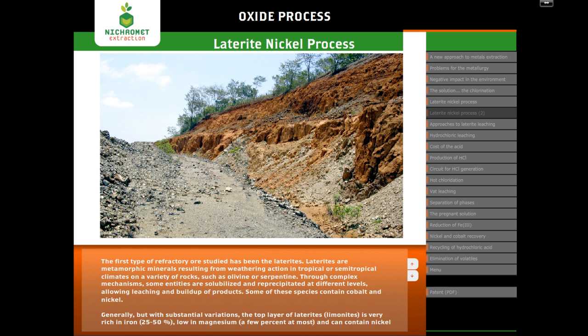Through complex mechanisms, some entities are solubilized and reprecipitated at different levels, allowing leaching and buildup of products. Some of these species contain cobalt and nickel. Generally, but with substantial variations, the top layer of laterites, limonites, is very rich in iron, low in magnesium, a few percent at most, and can contain nickel and cobalt at the level of up to 1% and 0.1% respectively.